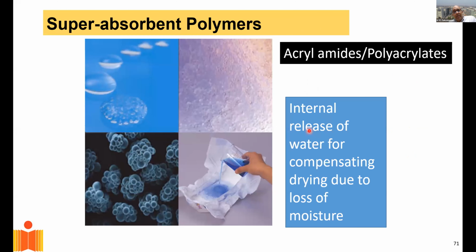There's another set of additives that we're adding into concrete. These are called superabsorbent polymers. Superabsorbent polymers are what go into diapers. These are materials that absorb water, they hold on to water. We mix them into concrete or cement paste, and the superabsorbent polymers absorb moisture, they swell, and they basically retain water. And when the concrete starts drying, which produces shrinkage, the SAP releases the water into the concrete mix and